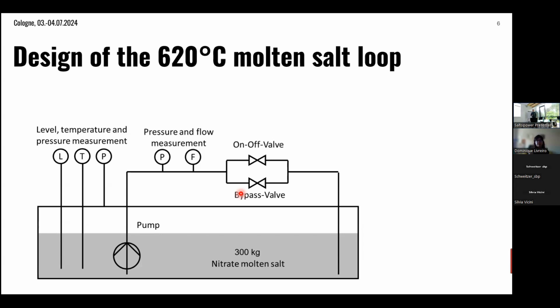So the loop basically is an oven. You have approximately 300 kilograms of nitrate molten salt. We have inserted a pump from the top. We have a level measurement, temperature measurements. We have pressure measurements of the oven. We also have pressure measurements in the tank, in the molten salt loop at several positions. Here only displayed for one position, but we have more.